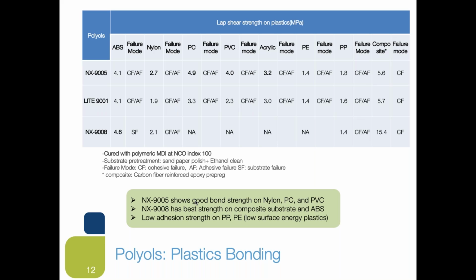From here, the key failure mode has been cohesive and adhesive combined, those types of failure. However, when the adhesion strength exceeds the strength of the plastics, we have also seen substrate failure as well, because the resin itself, the pure resin itself, was stronger than the plastic.